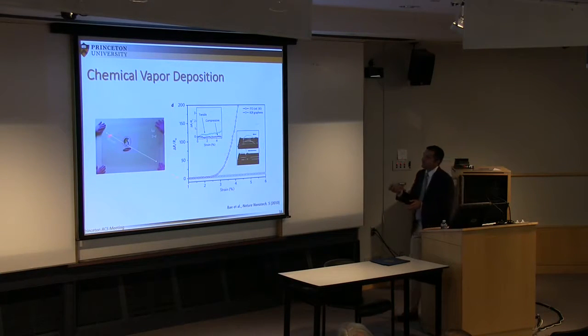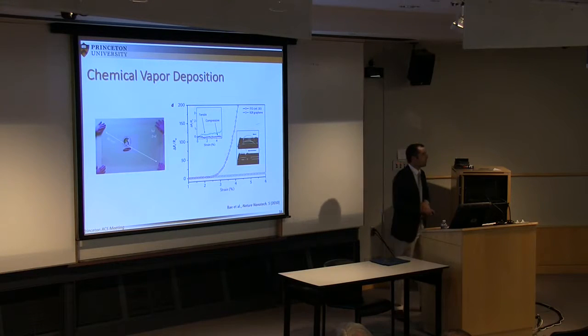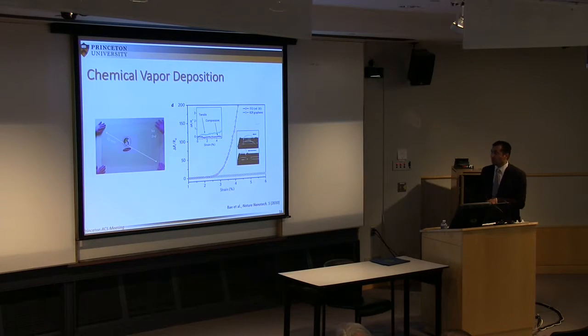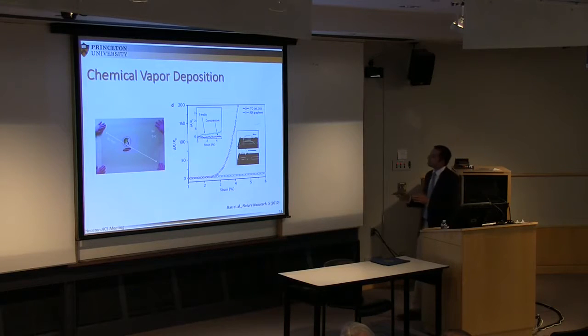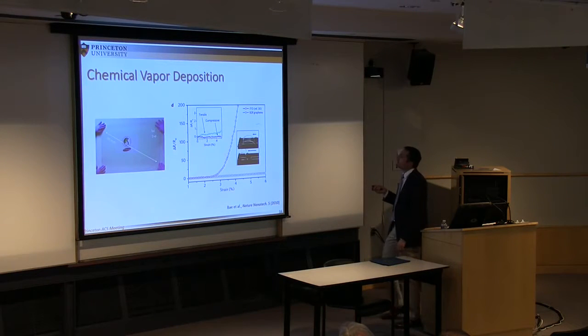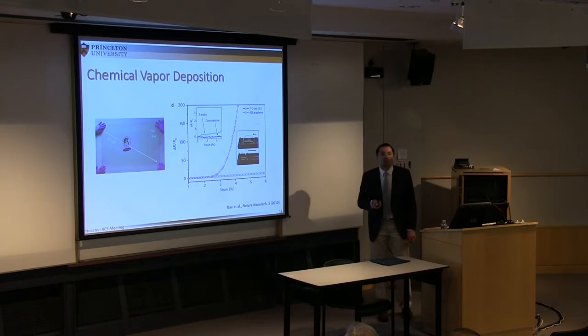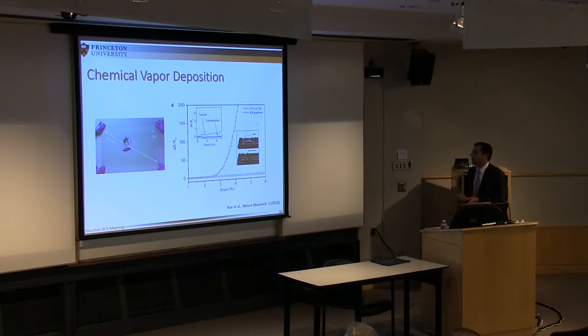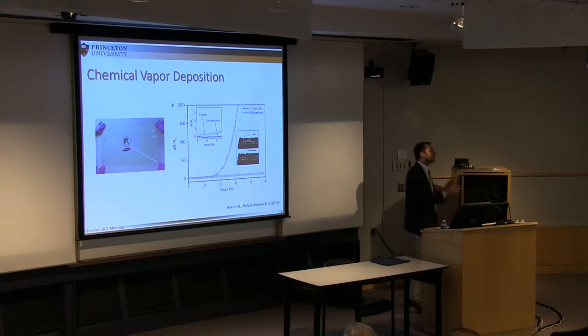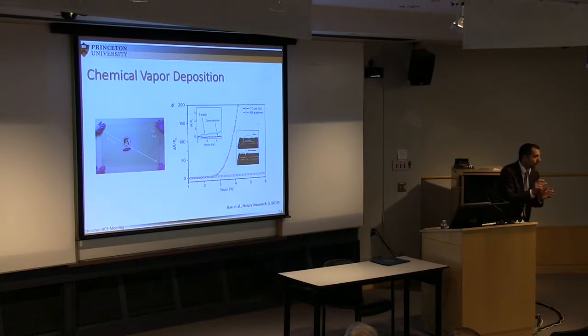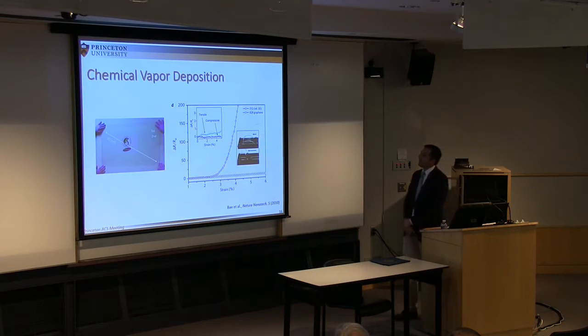You can have 30-inch in diameter graphene films, which is impressive. And then it's transparent, and it has decent electrical properties. So if you compare here the properties of graphene, we are measuring the change in the resistance as you are stretching your material and normalizing. You see that in the case of graphene, as you are stretching up to 6%, just to give you an idea, 100% would be you deform the object by twice its initial size. So 6% is still low, but anyway, the resistance doesn't change.